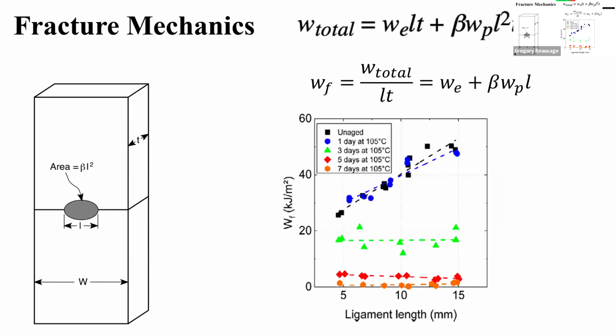So you've got that piece of plastic in the middle, that's L, and then you pull, and you ask how much work do I have to put in to get the whole thing to go to failure? That's what I'm plotting here: the work to failure as a function of that ligament length. Now there are two pieces to it. When I pull a piece of plastic apart, I have a zone of plastic deformation, and then there is the essential work of running that crack through the sample.